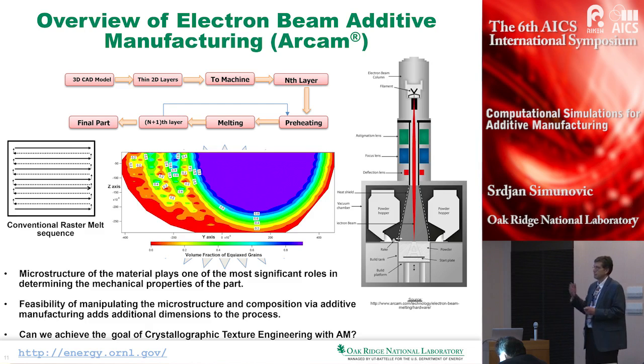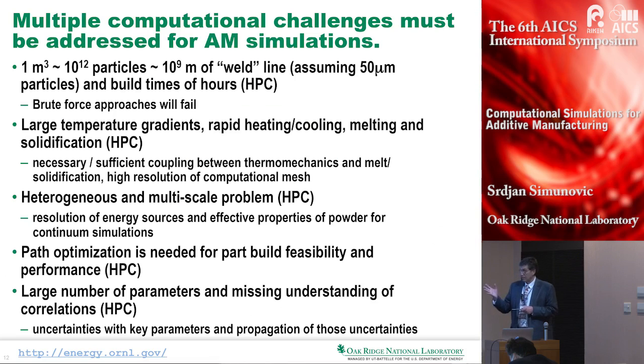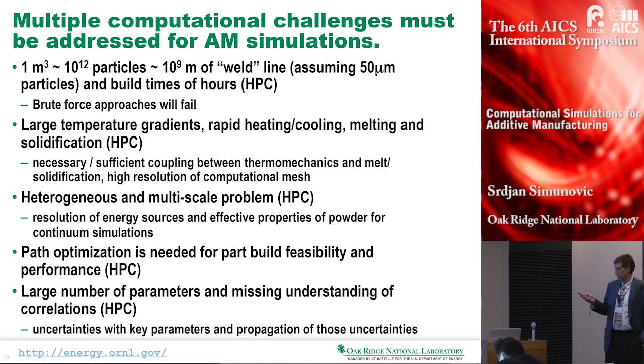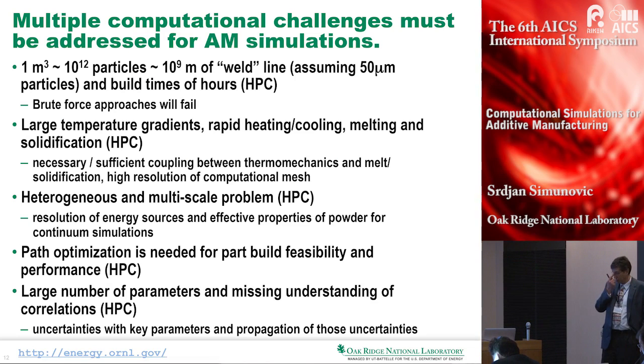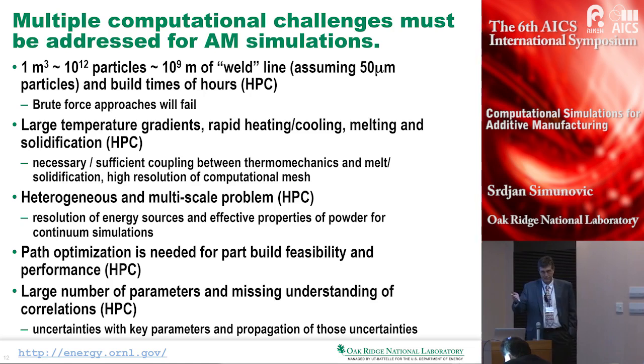So imagine having a turbine blade that has a tailored microstructure for the different locations on the turbine blade, which needs to meet different loading conditions. So this is the goal of this crystallographic texturing engineering. There are multiple challenges, obviously, for high-performance computing of this process. If you look at a 1 meter cube, which is a fairly large object, for the metal powder bed, it has about 10 to the 12 particles, and there are 10 to the 9 meters of weld line of melting this material as it's being built.